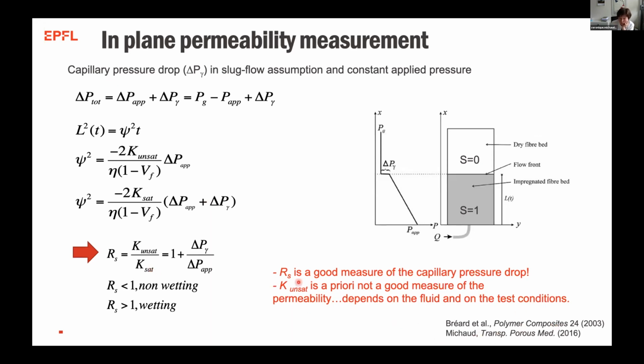Joël also from a long time ago has started to talk about this. And people have been measuring this K unsat over K sat, and they see that it's not equal to 1, but it should be equal to 1 only if delta P gamma is completely negligible compared to the delta P, the applied pressure that you put in your measurement. And we say that this ratio, if it's below 1, you have a non-wetting case, and if it's above 1, you have a wetting case. So in this case, RS is a good measure of the capillary pressure drop, at least we hope so. And this K unsat is a priori not a good measure of the permeability because it will depend on the fluid and the test condition and the ratio of this delta P gamma over delta P.